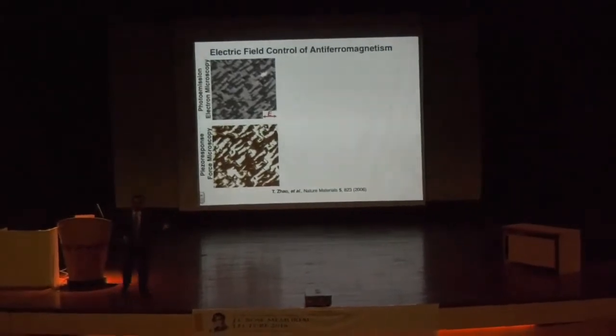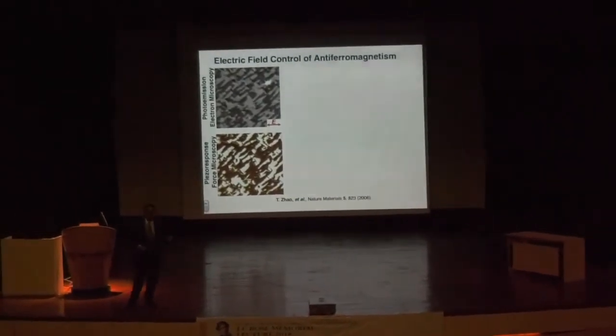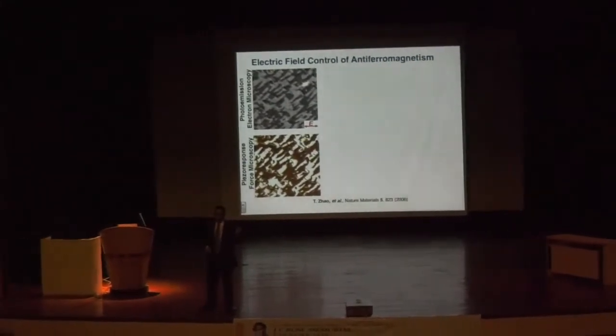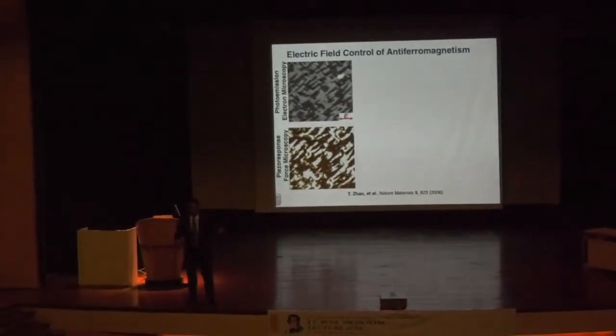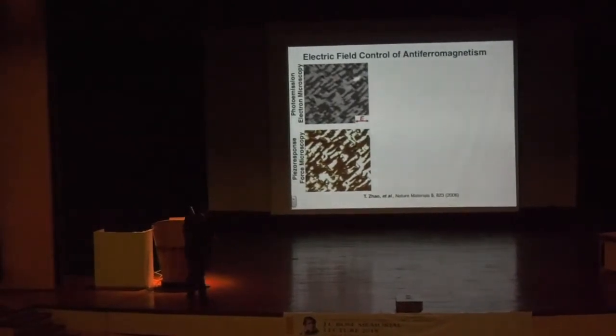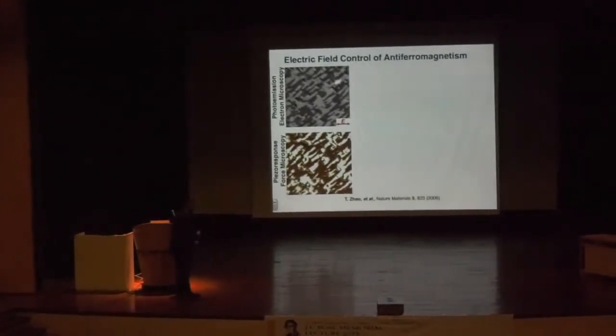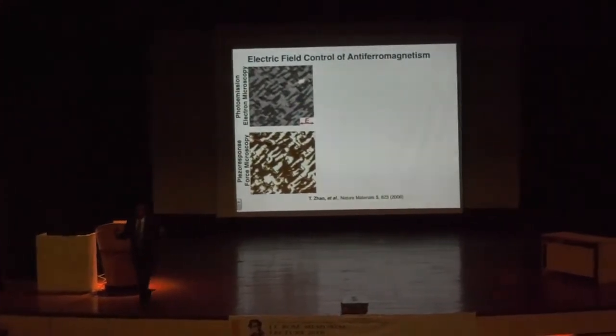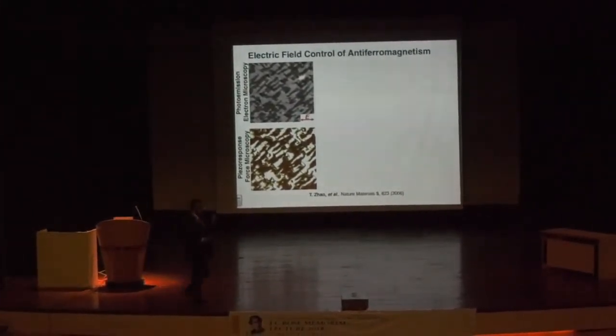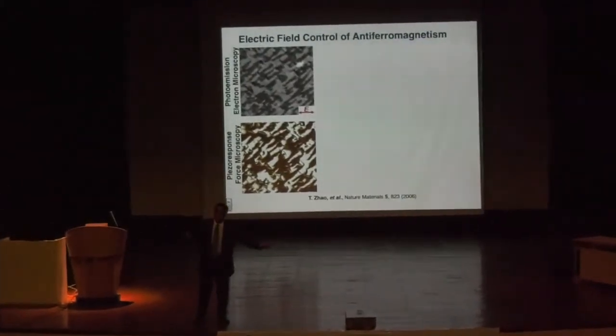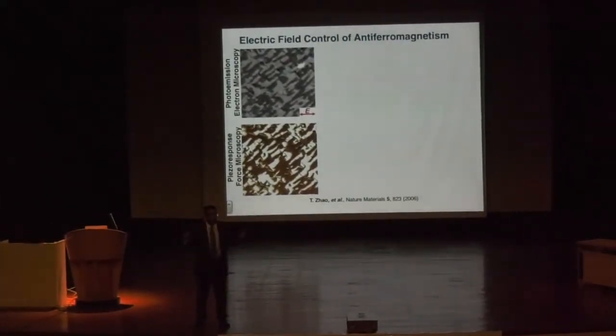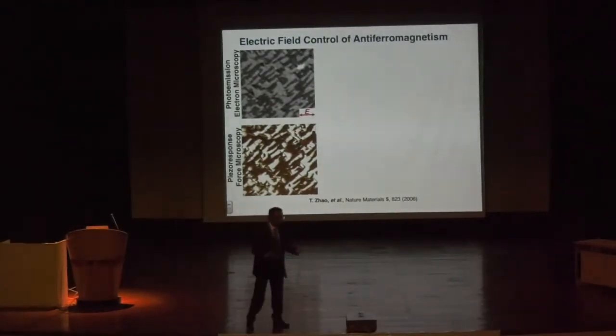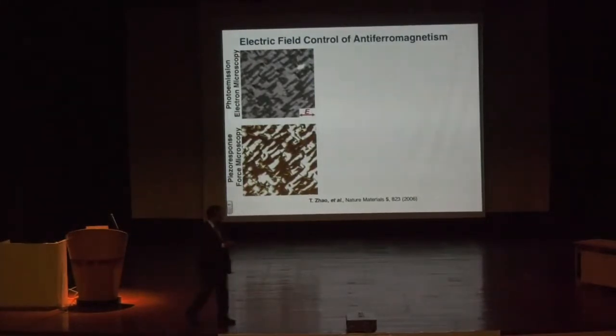I can take exactly the same region by putting markers and put it into a photoemission electron microscope and use linearly polarized X-rays and ask the question, what happens? And what you see is an image that looks kind of very similar to this. And in this particular case, depending on how you image, we use the iron absorption edge to do the imaging. Depending on whether you use the L2 or the L3 edge, you get some complementary information. But it basically maps out a combination of ferroelectric polarization and antiferromagnetism. Conversely, if you had a ferromagnetic layer, you could use circularly polarized light, and you can map out ferromagnetism.